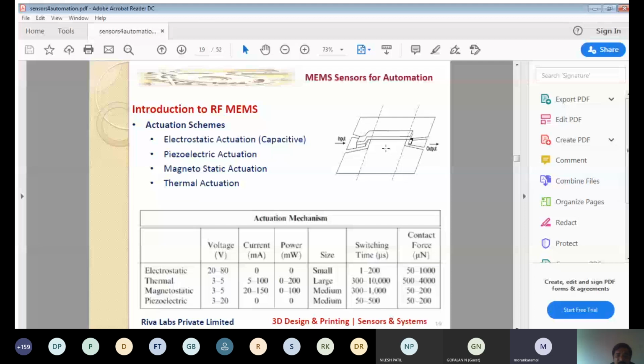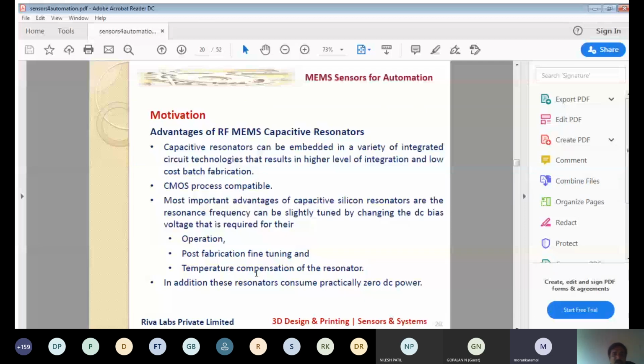So therefore, temperature compensation of the resonator is possible with electrostatic, because you need a temperature compensation. Whenever your MEMS are used in another environment where the temperature is very high, you can do temperature compensation in the case of electrostatic activation. But you cannot do it in the case of magnetostatic or thermal, because it depends upon the current, and the current will flow depending upon the resistance. So changing the forces is not very practical in the case of other activation mechanisms as compared with the electrostatic activation mechanism.